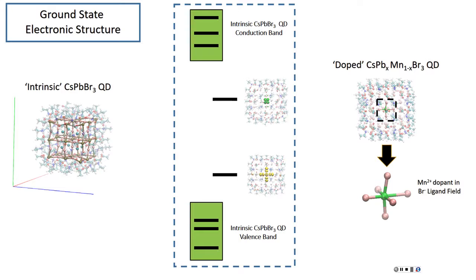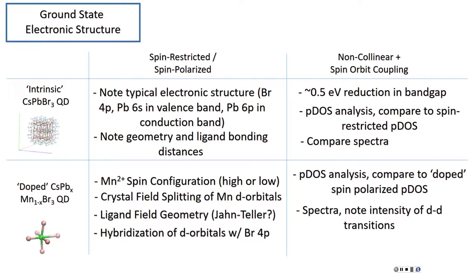But in your case, and for your results, when you explain your system, you probably will point out that it's like octahedral, but it's really perturbed octahedral. Well, it looks octahedral, but I don't know, explain it. It's perturbed octahedral due to the manganese. If it's lead inside, then all the bond distances are relatively the same. But when you substitute in manganese, then you have some contract, some elongate, and it's a perturbation, a different environment. So that's what I planned on talking about next.